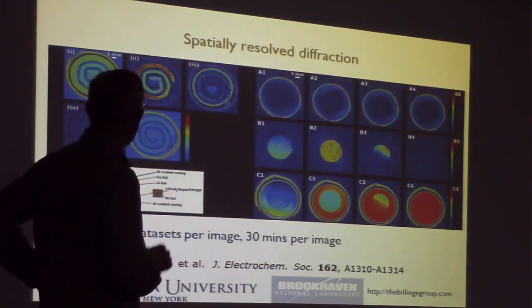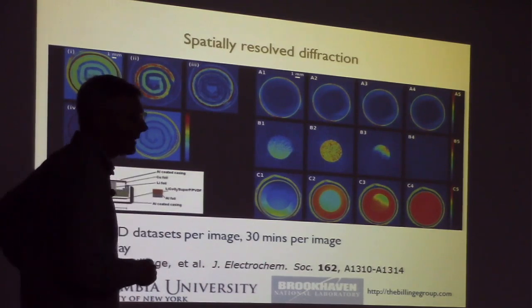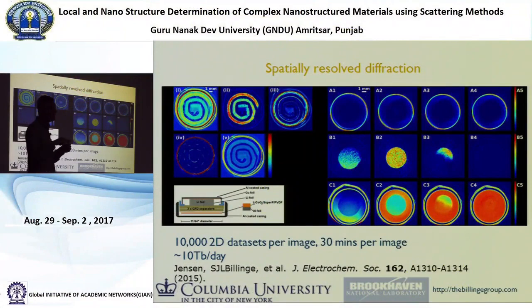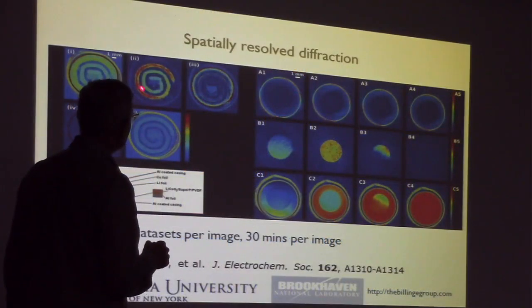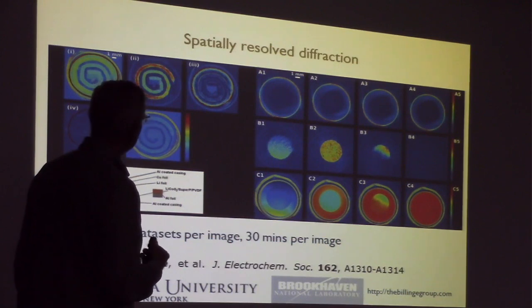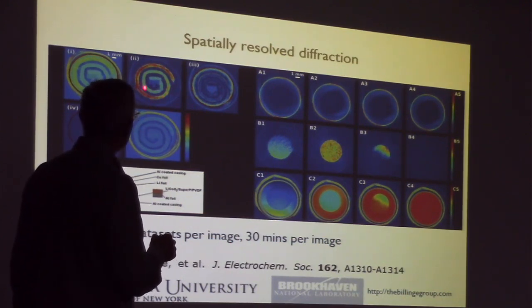And then you can do nice things with batteries, for example. So this is a nickel metal hydride rechargeable battery. And it turns out if you cut those open, they have this nice spiral wound. So they basically take a cathode, electrolyte, anode sandwich like that, and you roll it up like a jam roll. And this is just an electron density measurement, but we can find the pixels which contain the cathode material, and we can fit the structure of the cathode, and we can see it here. And we can do the anode, which is here. The anode is much thinner than the cathode.